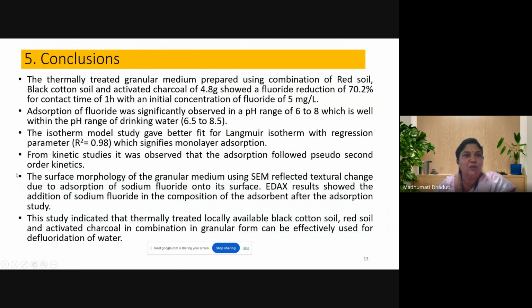So finally, to conclude, the thermally treated granular medium prepared using a combination of red soil, black cotton soil, and activated charcoal of 4.8 gram showed a fluoride reduction of 70.2% for a contact time of 1 hour with an initial concentration of fluoride of 5 milligram per liter. And adsorption of fluoride was significantly observed in a pH range of 6 to 8, which is well within the pH range of drinking water suggested by the Bureau of Indian Standards, which is 6.5